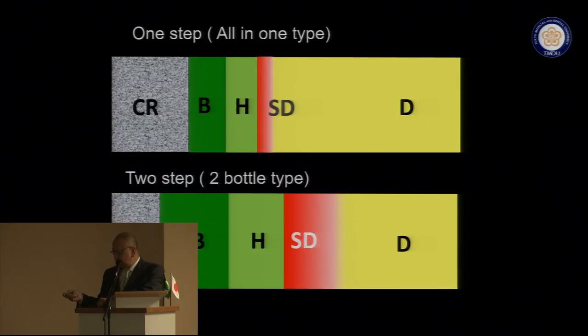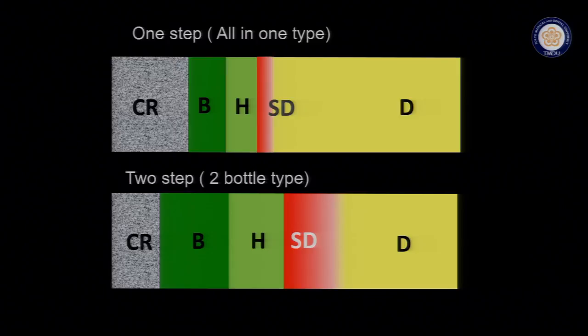However, in the case of one-step self-etching system, it can create the super dentin, even though the thickness is very small. And unfortunately, the weakest point may be at this part in the case of one-step self-etching. In the case of two-step self-etching, to make the bonding interface much more stable, we need to detect the weakest point at the interface, even with two-step self-etching.